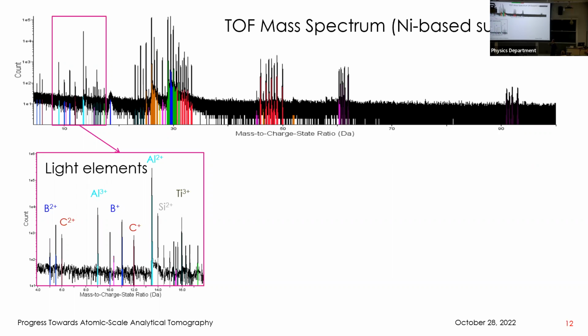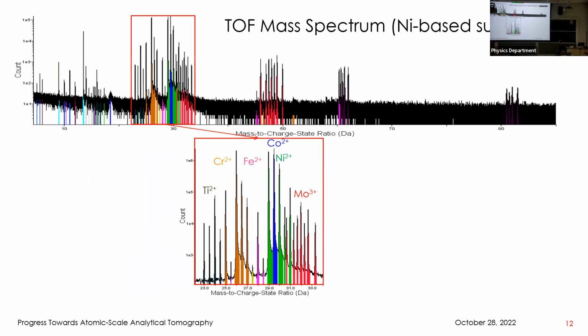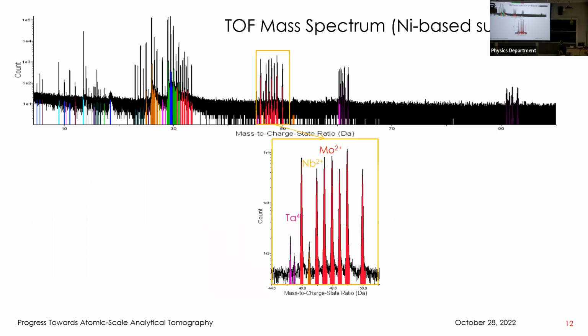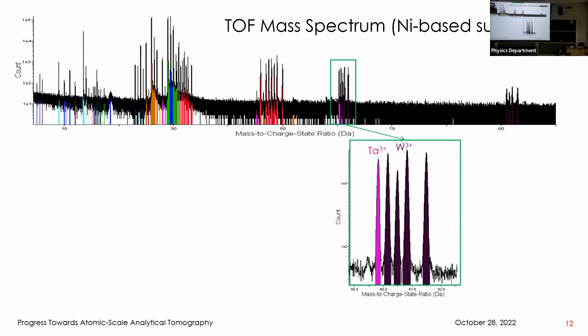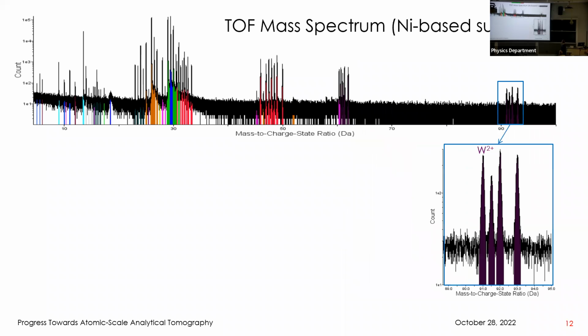It's based on time of flight mass spectrometry. So you can see, for example, boron and carbon here, you can see lithium. We can even see hydrogen. In fact, those 3 peaks there are associated with hydrogen, hydrogen 2, and hydrogen 3. You can also see some of the transition metal elements, which typically field evaporate as a +2. And then you can see some others here. There's the molybdenum, many isotopes. This is another very important thing. You see all the isotopes, not just the elemental identification. And in some applications, isotopic identity is essential and very helpful. Just to finish out, there's a +3 of tungsten and a +2 set of peaks.